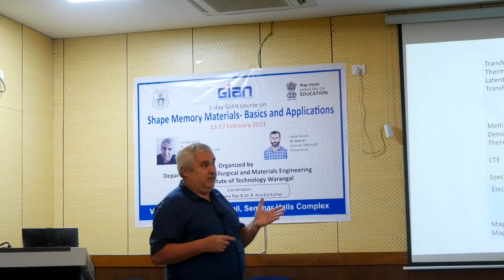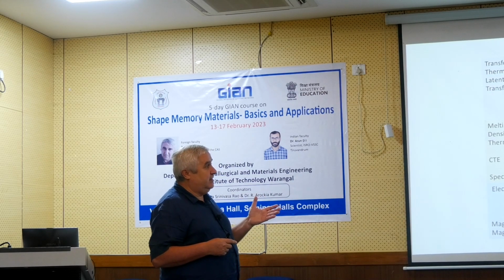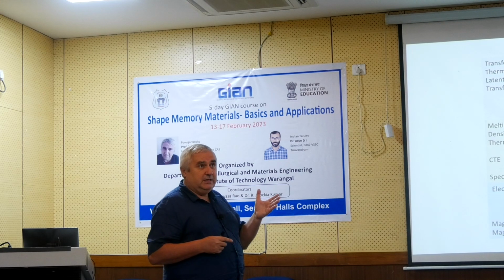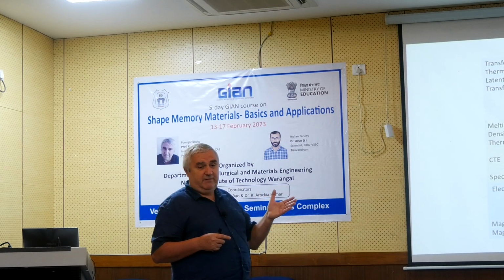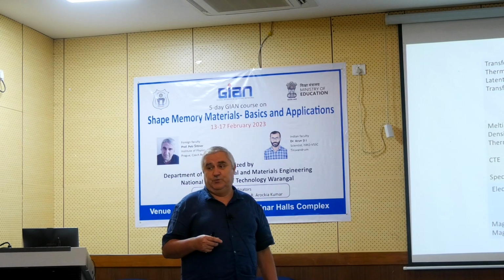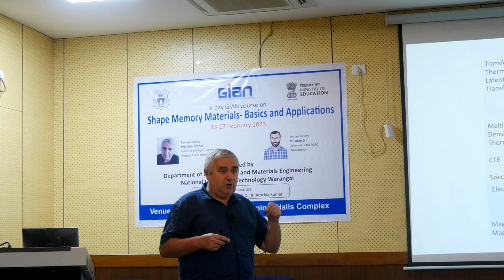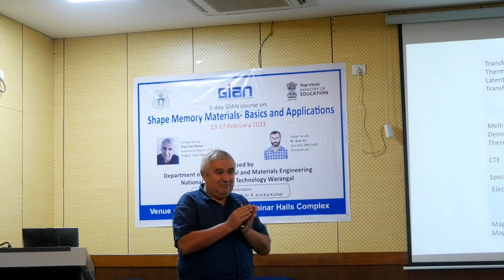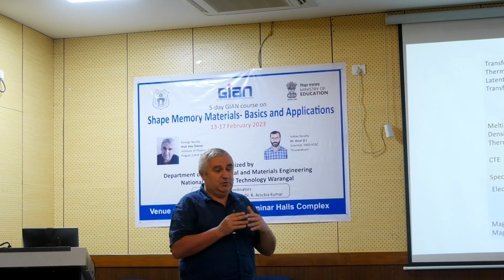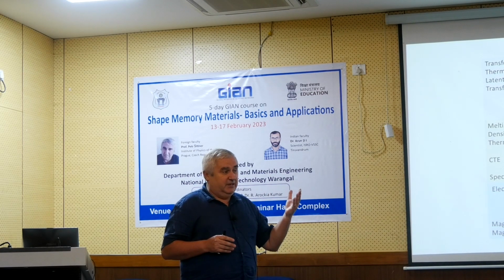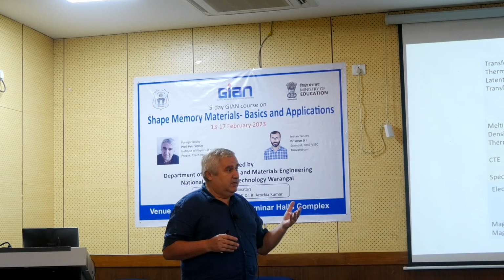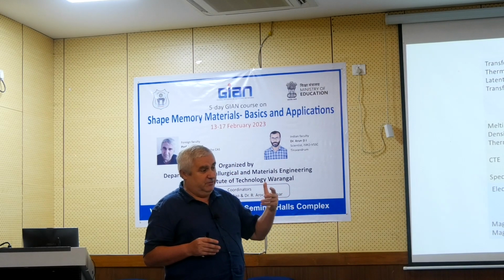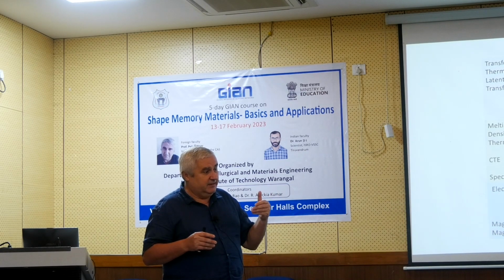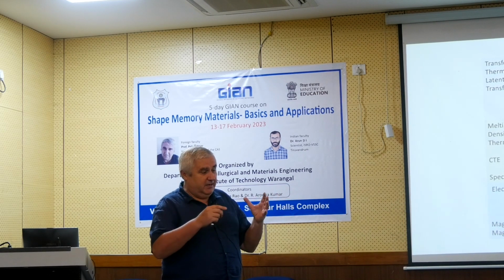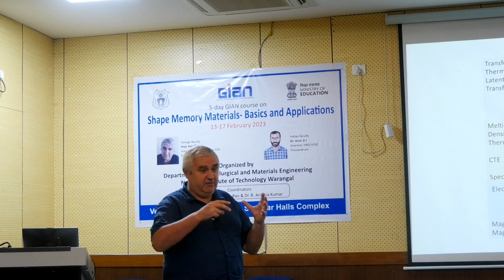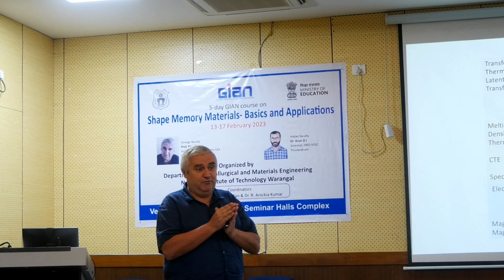This is different with maybe NiTinol. If you want to decrease it, nickel titanium copper alloy works very well. It has hysteresis of 10 to 15 degrees, because the copper affects the strain compatibility condition at the habit plane. So you can find in the literature papers about the so-called lambda cofactor, which means that by adding the copper to nickel titanium, the lattice parameters are changed in such a way that this compatibility condition is easily fulfilled.